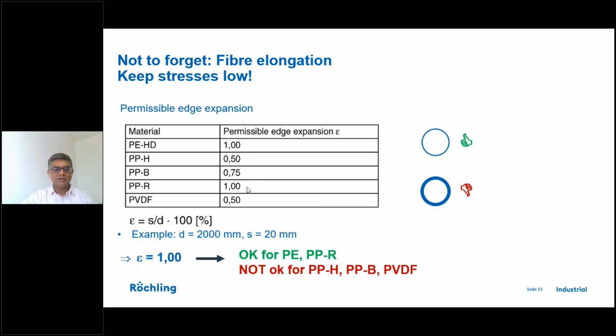What does this mean? If you have 20 mm as a thickness, and the edge expansion is 1%, then you can make a cylinder of 2 meters. Similarly, if you have a 20 mm thickness and you have 0.5% as the edge expansion, then the diameter has to be 4 meters, so that you do not have a problem of V-notch creation on the outside surface of the sheet.